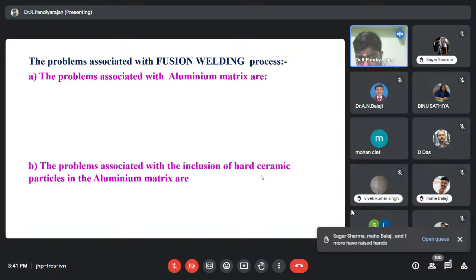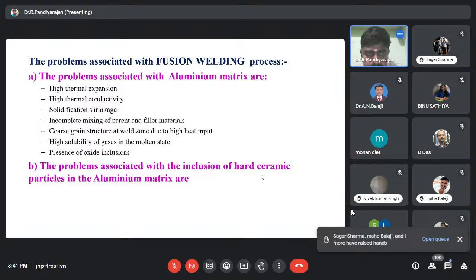Second problem is the problem associated with inclusion of hard ceramic particulates in aluminum based composite material. The first problem is the aluminum matrix problem: high thermal expansion, high thermal conductivity, solidification shrinkages, incomplete mixing of parent and filler materials, coarse grain structure of weld zones, and the presence of oxides in situ.